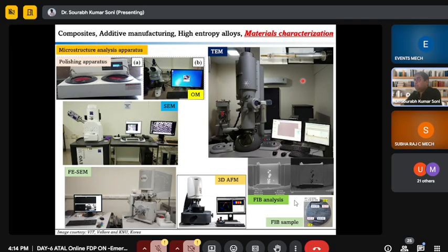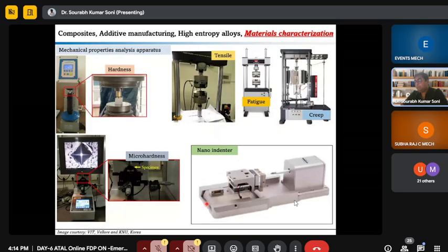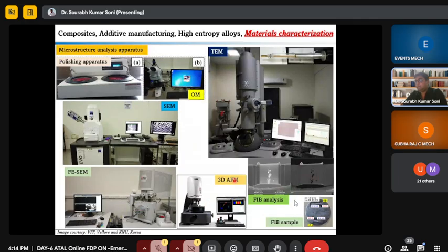This is the TEM. If you want to observe at the micro level or even up to the atomic level, you can use the TEM also. This is the FIB. Before going into the TEM, you have to do the FIB. In FIB, within the FESEM they fix the specimen, and within the FESEM they also identify which part you want to analyze in the TEM, so they can fabricate it. This is the FIB specimen. And this is the 3D AFM, which we can use to analyze the surface profile of the specimen.